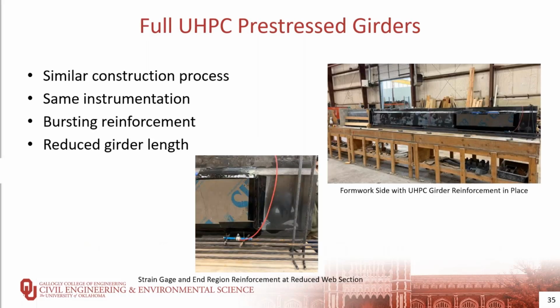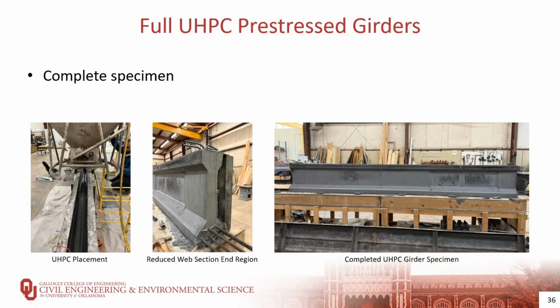Moving on to the UHPC pre-stressed specimens. So those were all full UHPC specimens. The construction and the instrumentation for them were similar to the hybrid girders. No shear reinforcement was added, but only bursting reinforcement was added to the ends as shown in the bottom figure on the left. And again, these specimens were 14 foot long instead of 18 feet. Here is a few pictures starting from the left showing the UHPC placement, the reduced web section at the live end region, and the complete UHPC girder specimen.